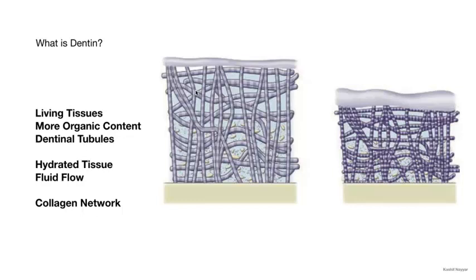Okay, and if you over dry the dentine, you are basically desiccating it and removing the excess water. And when the water is evaporated from the dentine, the upright collagen fibers are just collapsed and leaving a very less surface area for the bonding resin to penetrate. Okay, so that's why you get less bonding strength, and it is never recommended that you desiccate your dentine. Always, always, always keep your dentine slightly moist so your bonding resin can better penetrate and give you excellent bonding strength.